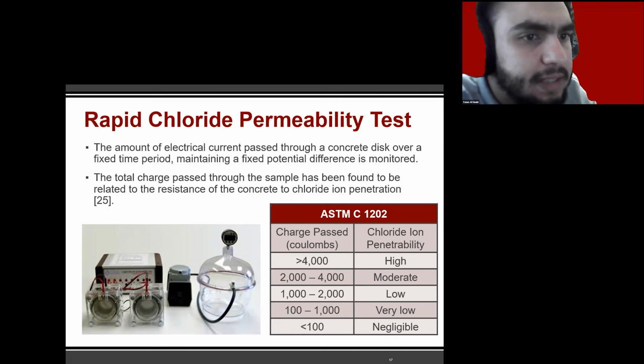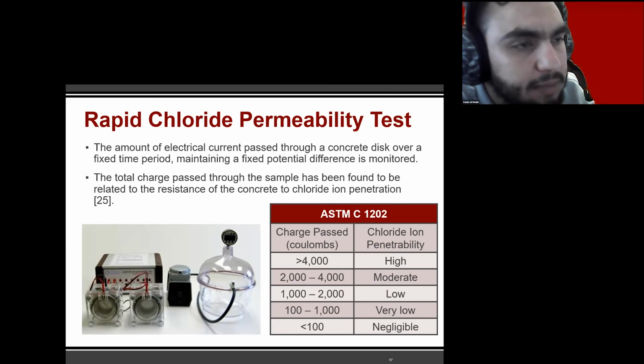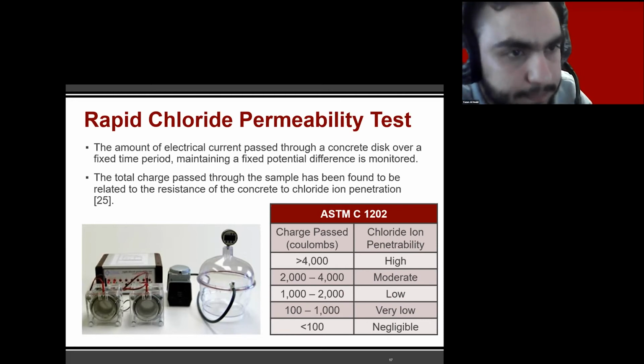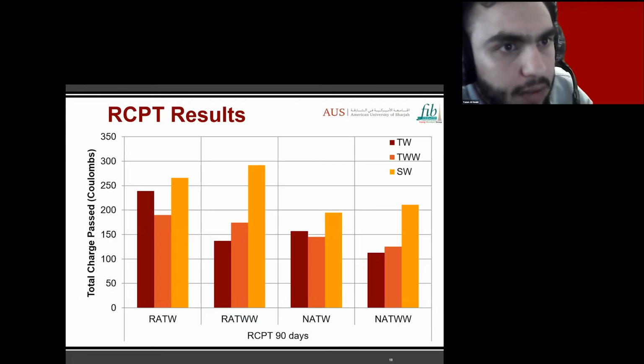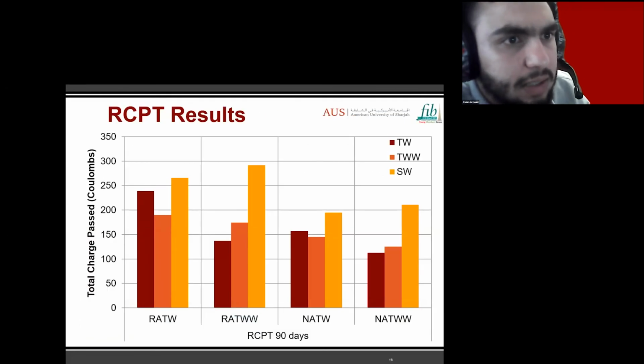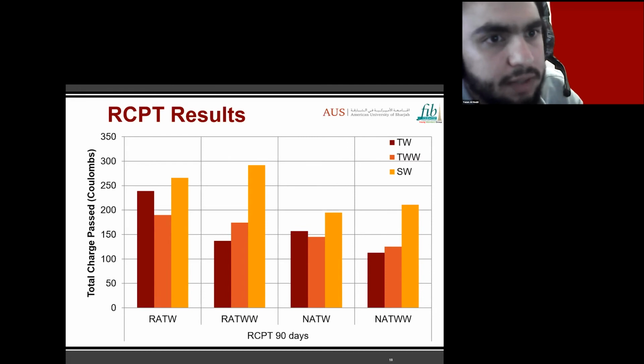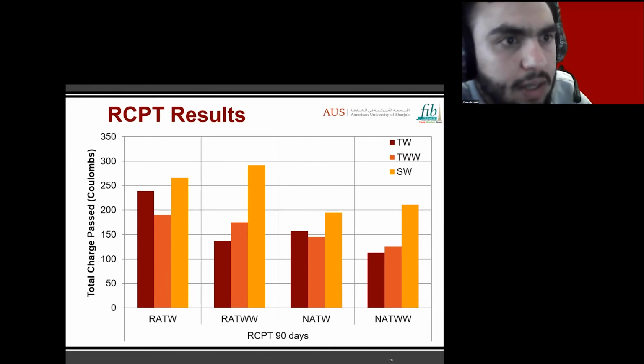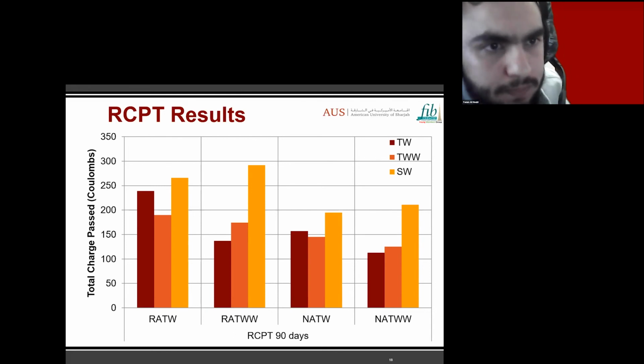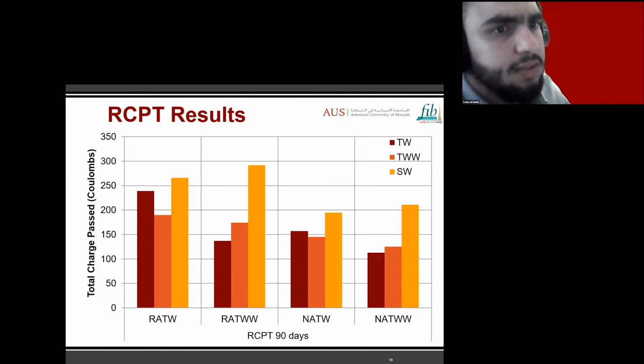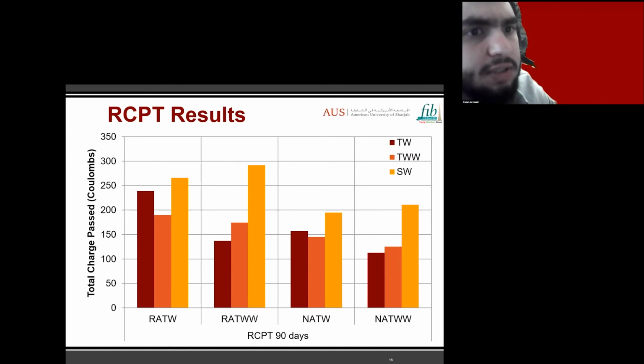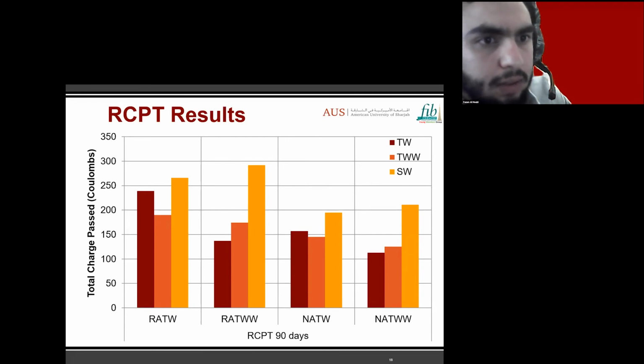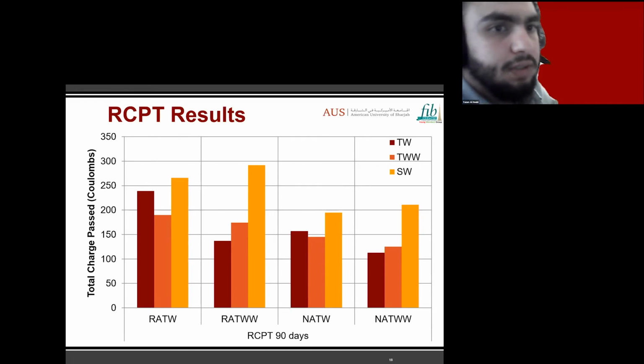The standard provides a classification for each range of charge passed, and it can be summarized in the table seen in this slide. The results indicate that the 12 mixes are classified under the very low permeability class, as they lie within the range of 100 to 1000 coulombs as per ASTM C1202. This implies that all mixes are considered durable in terms of chloride ion penetration, and the use of 20% recycled aggregate and treated wastewater can be considered in concrete subject to all different environmental conditions.